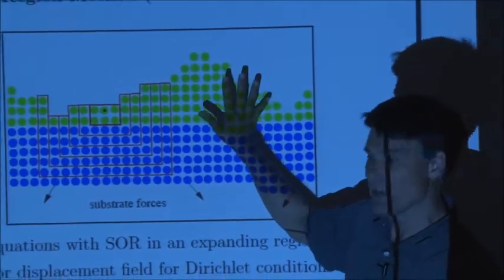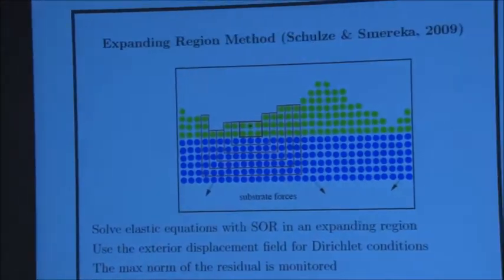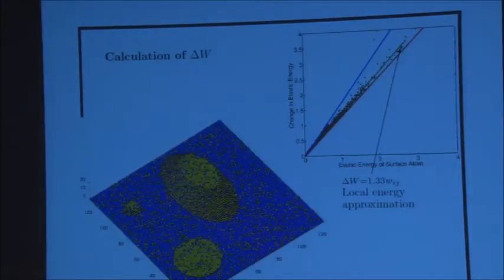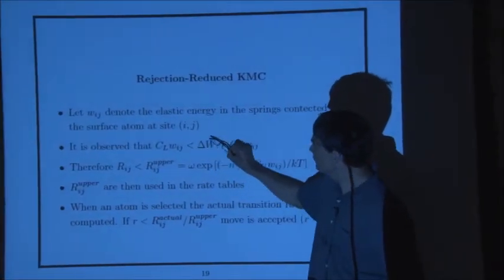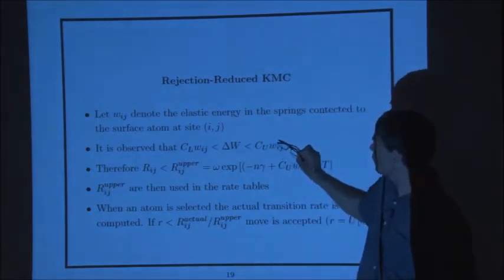For the upper and lower bounds: here is an artificial test case we made — a bunch of random structures designed to be maximally complicated. For every single atom on the surface, we removed it, relaxed the system, and computed with high accuracy the total change in elastic energy. Along one axis is the total change in elastic energy; along the other is WIJ, the energy in the bonds immediately broken when that atom is removed. We did that for every single atom — all the black dots are there.